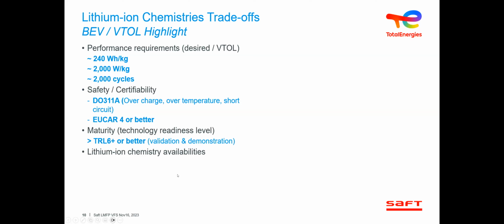So if we take the battery system for VTOL and try to do highlights for lithium chemistries, the target on the electrical performance is to be greater than 240 watt-hours per kilo. That's a good number. Even if it's challenging, it's still a number that tries to be pushed towards higher figures, 2,000 watts per kilo. Combined, it should also offer 2,000 cycles.